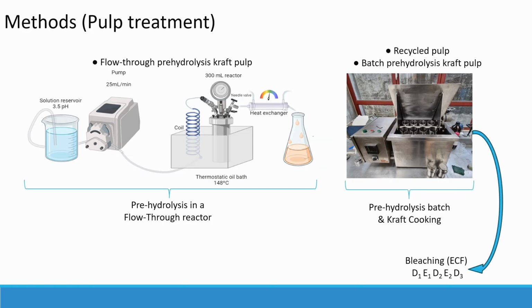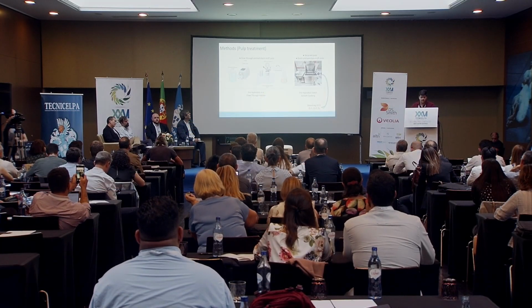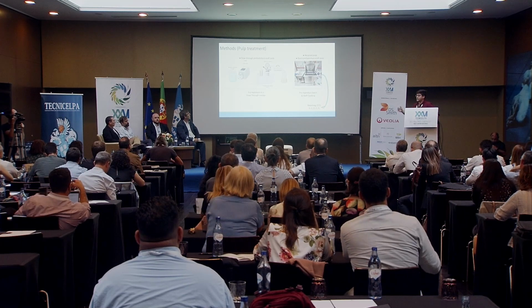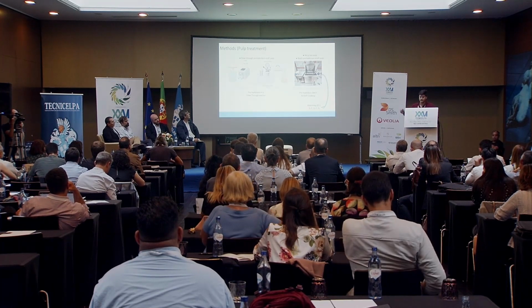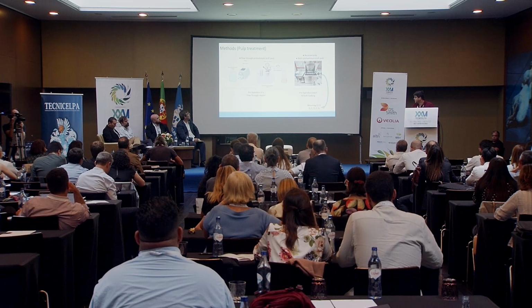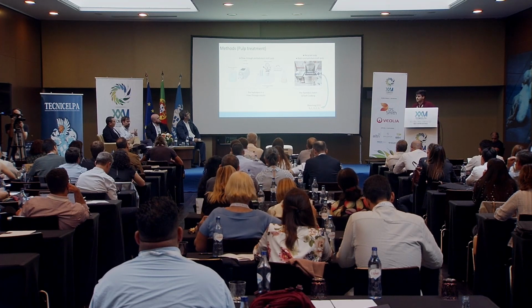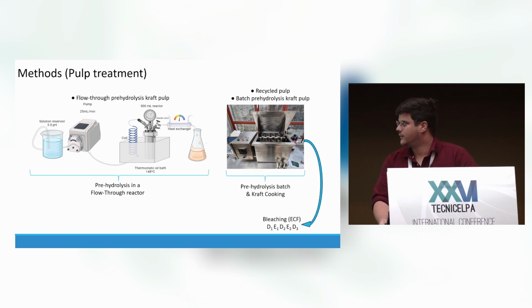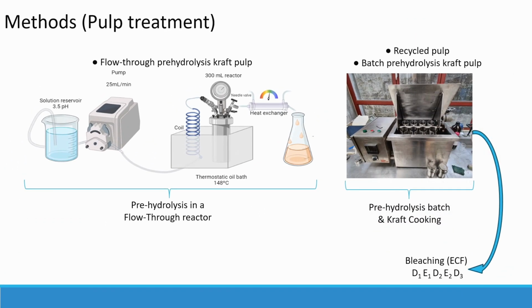So regarding the methods, we can split this work in 2 parts. In the first study, we studied the flow-through PREHYDROLYSIS KRAFT pulp. It's the scheme represented. As I said before, my PhD focused on the PREHYDROLYSIS KRAFT, and this is a previous work where we studied the valorization of the hemicellulose removed during the PREHYDROLYSIS. With this method, we were capable to control the pH of the solution used, the flow of the solution in the reactor, and the temperature of the reactor. This pulp will be compared with the standard batch PREHYDROLYSIS shown on the right.